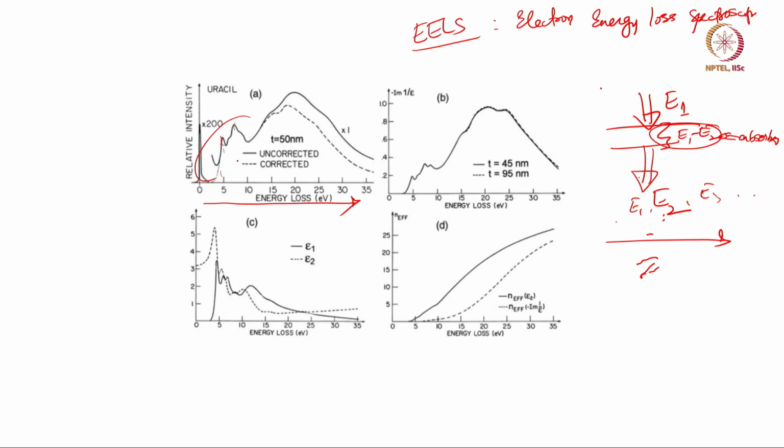So you have all these various absorption processes. This is analogous to looking at the imaginary part of the refractive index, or just the absorption coefficient. This goes from a range of 0 electron volts all the way up to 35 electron volts. And I keep saying that at about 20 electron volts there is what is called a plasma peak, a plasmon oscillation from the valence band, the valence band plasma.